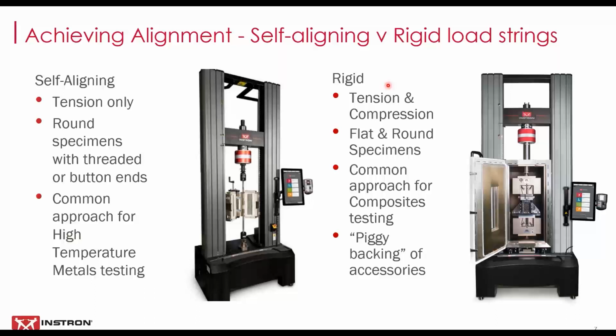When we're looking at a load string for both tension and compression, and also for use with both flat and round specimens, particularly composite laminate specimens, we really need a rigid approach, a rigid load string. This is an example of a rigid load string, in this case for operation inside a temperature chamber, but it could be for operation at room temperature. This load string will achieve good alignment in tension and compression, and it will support the ability to what we call piggyback, or to mount other accessories in between the main grips. So those are some of the advantages of that approach.